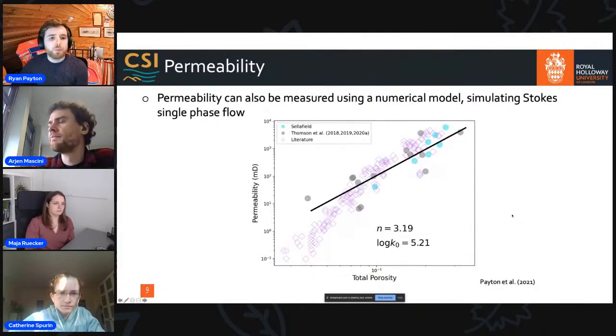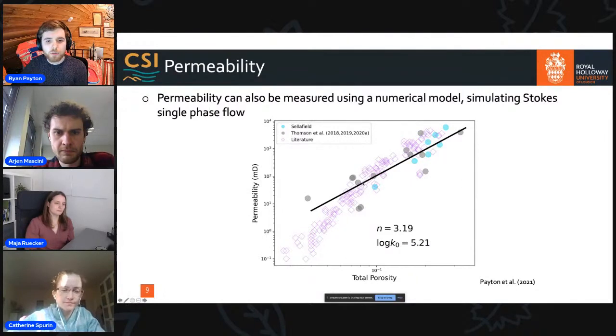So we're also able to make permeability measurements as well. We run single-phase Stokes flow through the pore network, and we can see here that with the Sellafield results, because they're up on this end, we get this nice sort of trend here that you can see, while using the data from the literature.